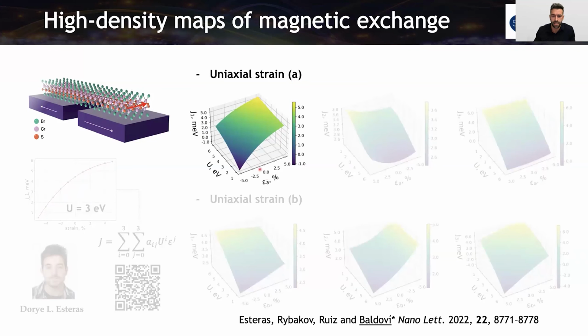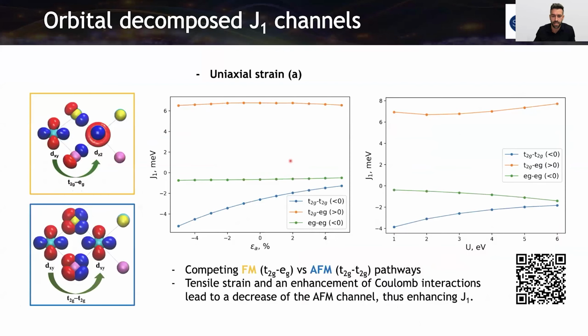Interestingly, as I said before, J1 is very connected with the A-axis. So we are here applying strain along the A-axis. We're expanding the material, and J1 is clearly increasing, following this. And we wanted to understand what is the main effect doing that, so we go to an orbital decomposition of each one of the exchange interactions. This is something that TB2J allows, and we find two different pathways that are competing.